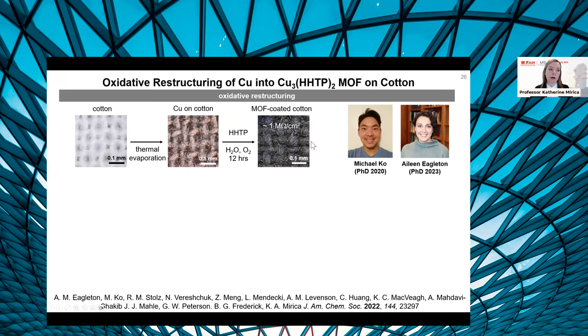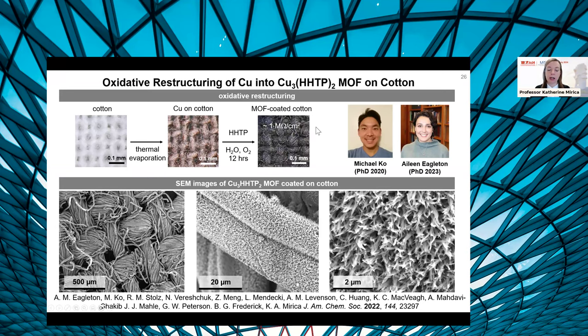So in this particular method, what we do is pre-deposit solid copper metal onto a textile substrate and then restructure it under oxidative conditions in the presence of oxygen, also in the presence of ligand in water, into the metal organic framework. And so this gives us conductive electronic textiles with metal organic frameworks embedded on the surface of the textiles, but also very good orientational direction of the metal organic framework crystallites on the textile substrate, and very good